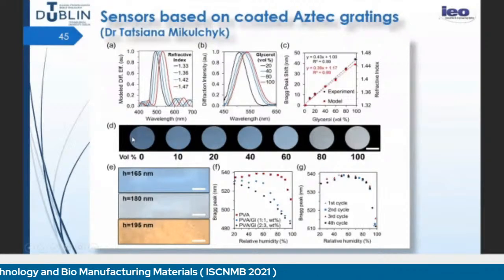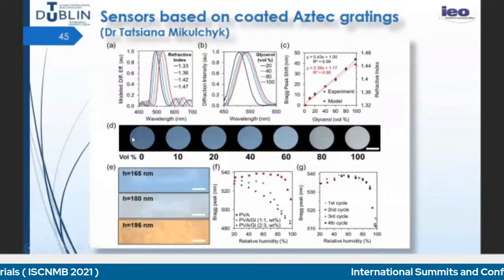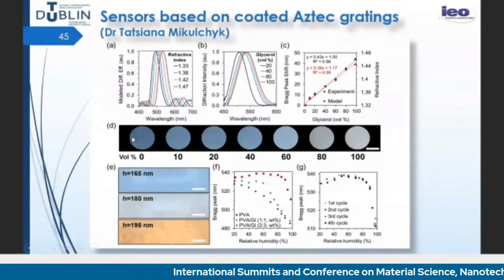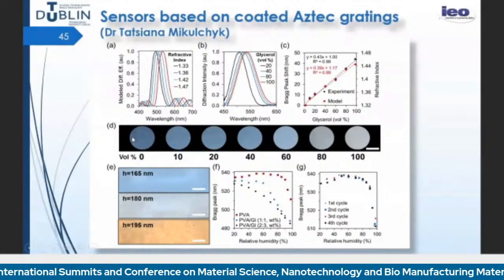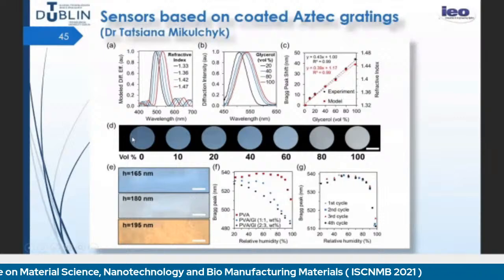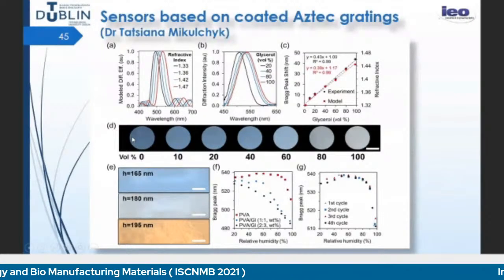Just some results from different step sizes, again, how it influences the diffraction efficiency. And here you can see how the wavelength shifts as you have different concentrations, for example, of glycerol in PVA. So again, depending on the refractive index and the absorbed analyte, you can get a wavelength shift in these structures.